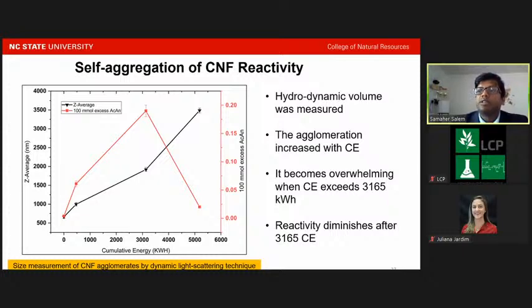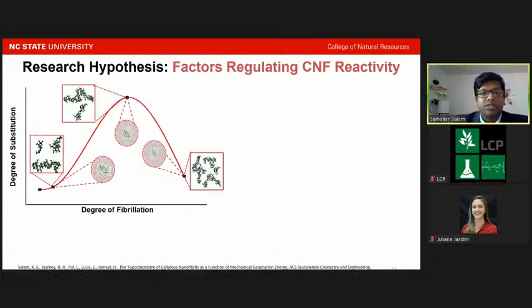The tendency of the nanofibrils to form flocculates by hydrogen bonding is due to their high aspect ratio and hydrophilic nature, which leads to self-aggregation of the surface. And thus, the reactivity diminishes after reaching the maximum. So this is our research hypothesis: the degree of substitution and the degree of fibrillation.